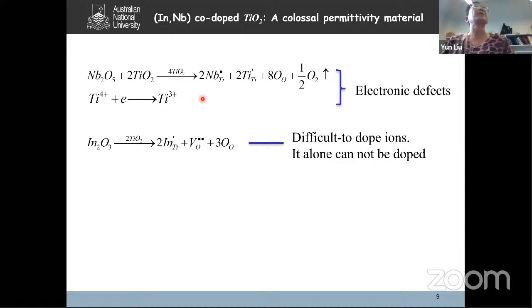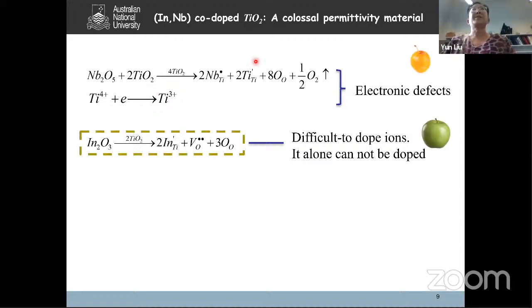So in that case, you can introduce electrons. You can dope in as much as you want, so this is an easy doping ion. And then indium is generally difficult to dope because it's too big in size and the electronegativity is quite different in comparison with titanium. So normally, with indium alone, you can only dope into the material a little bit, maybe less than 1%, or maybe even lower.